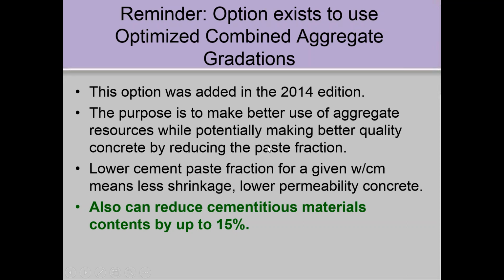And there are advantages doing that if you have enough bins at the plant to do that. Even 3 bins is sufficient. You can lower the cement content of the concrete, maybe up to 15%. And if you have less cement paste in the concrete, you're going to get less drying shrinkage. You're going to get lower permeability because permeability occurs through the paste fraction. So there's some economic advantages. There's also technical advantages to doing this.